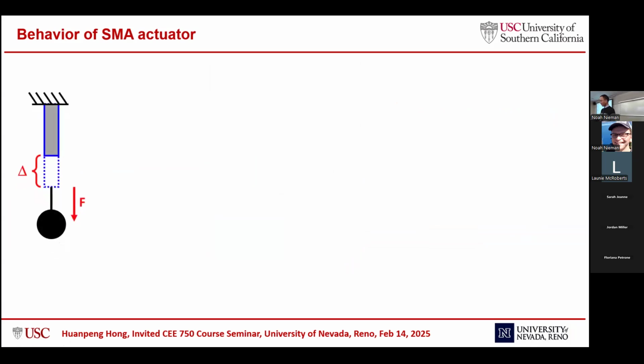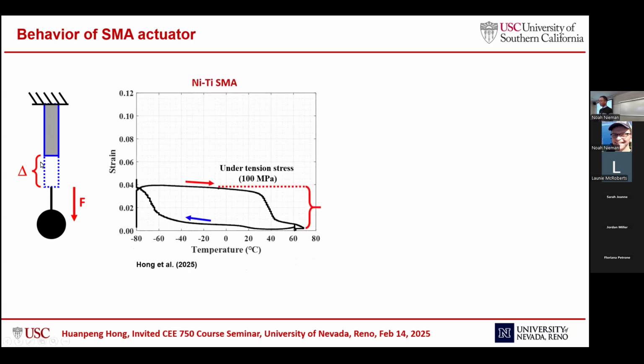So here's an example of the shape memory alloy actuator. This is the loading condition we use. We fix one end and give this material a constant force, and there will be a deformation. And if we lower the temperature down, it will shrink back. So this force and stroke is the target in this stress strain curve. Firstly, we will look at the nickel titanium shape memory alloy. If we start from minus 80 Celsius, heat it up to 80 Celsius and then cool it down to minus 80 Celsius, this is one cycle. We can do it repeatedly. Under a constant tensile stress of 100 megapascal, the actuation stroke, that is, the deformation of this material, can be around 4%.